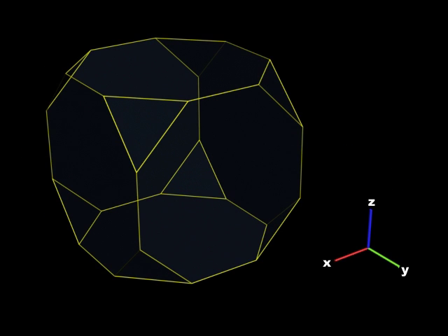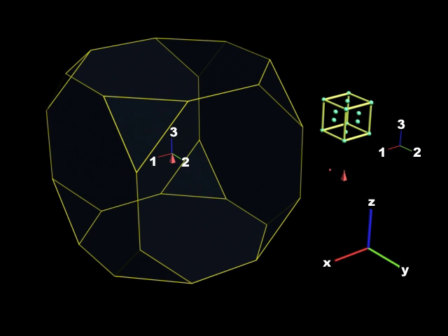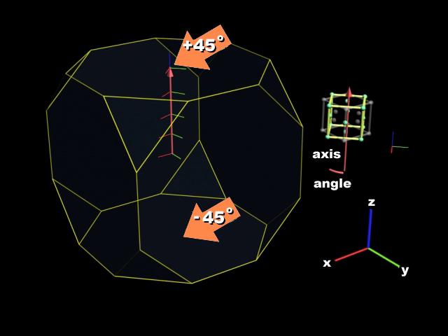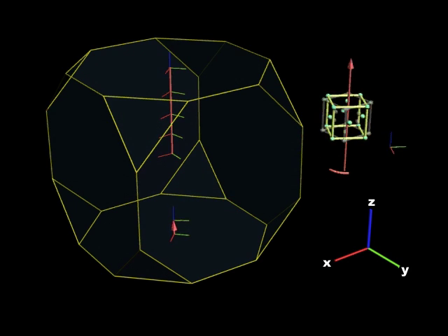Rotating around a single axial vector shows the symmetry of the FCC unit cell. For a cubic crystal, a 45-degree rotation about a 100 axis is equivalent to one of -45 degrees. We start with the crystal and sample axes aligned and rotate it about the sample Z axis, which is the crystal 100 axis. When the vector reaches the box boundary after a positive 45-degree rotation, we reposition it to its symmetrically equivalent point at -45 degrees of rotation. Rotating by 45 more degrees brings the FCC unit cell back to the starting point. The Rodrigues vector thus returns to the origin of the Rodrigues box.